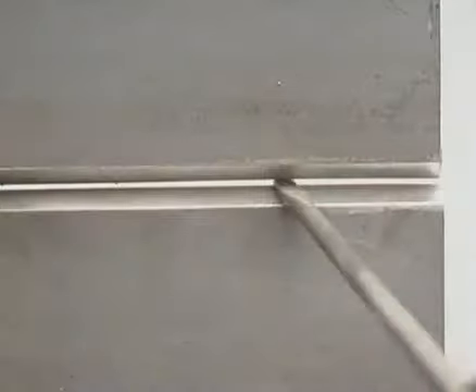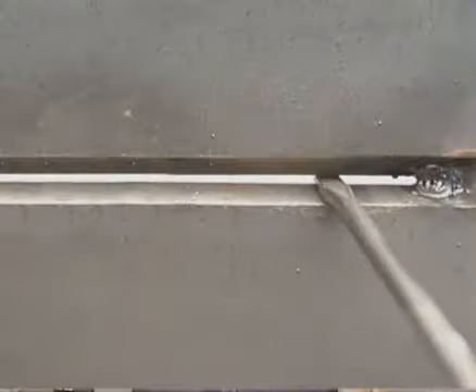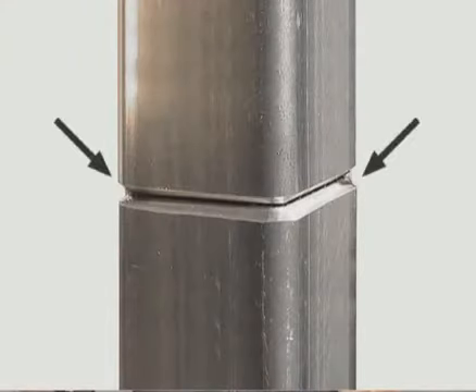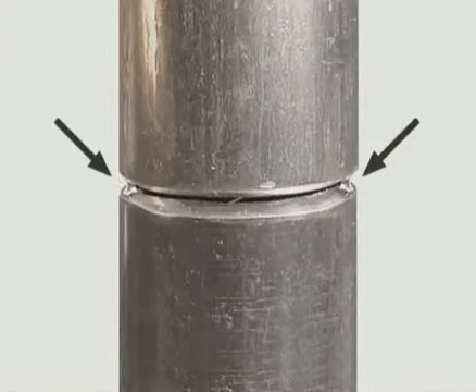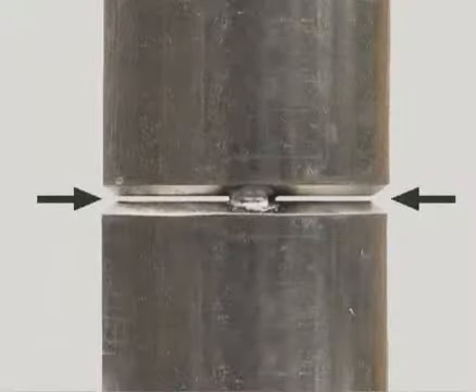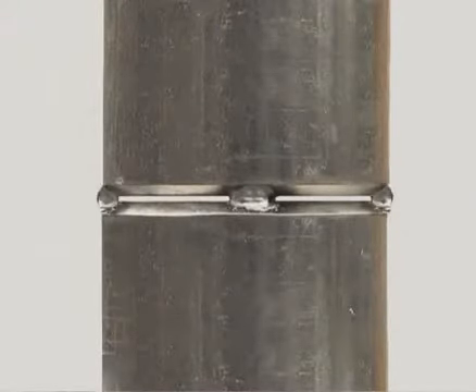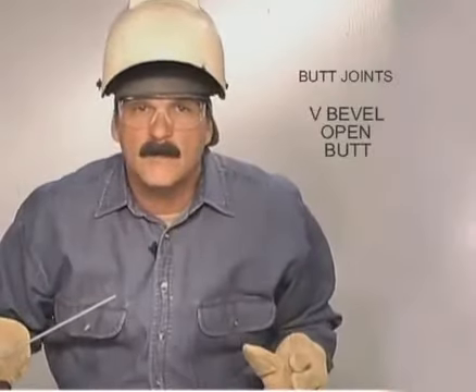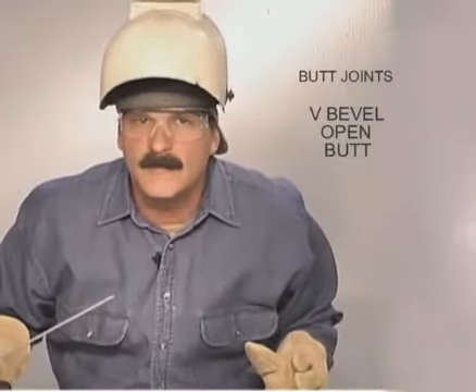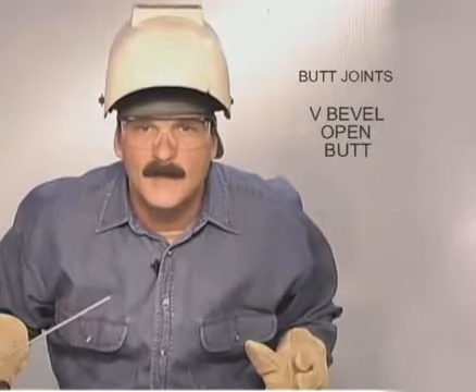On heavier pieces, after the first tack, use a small wedge or a screwdriver to keep the gap uniform. Because of the taper, you can remove these after the joint is completely tacked. On square tubing, tack opposite corners. For pipe, opposite sides. Make sure the gap is uniform, straightening when necessary, then put in 2 more tacks. Flat, horizontal, overhead, and vertical down root passes are all done the same way.